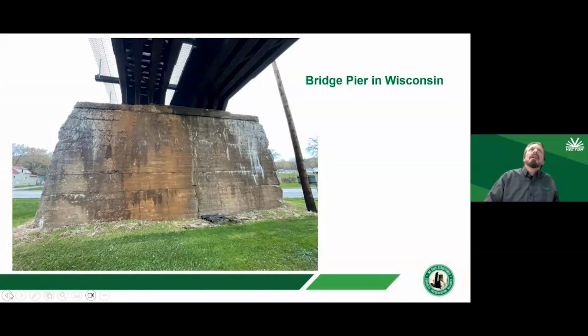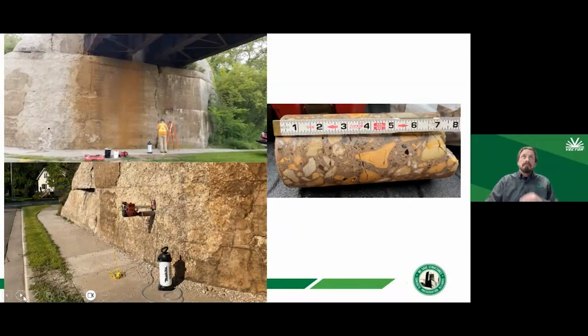Another project, similar, but a very different mode of deterioration. This was a bridge that was constructed in 1912. Back then, they didn't have a lot of reinforcing steel, so they didn't just cast mass piers and mass abutments. In this case, we're seeing some fairly advanced freeze-thaw damage of that concrete. You can see in the top left-hand corner there, and in the photo below it, an incredible amount of cross-sectional loss due to freeze-thaw damage.